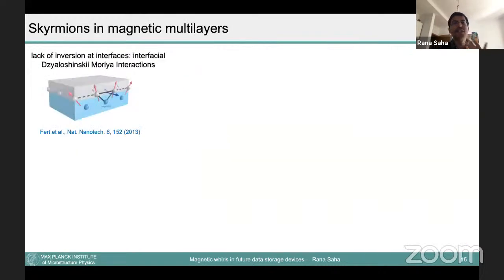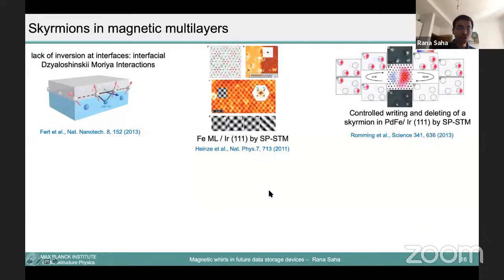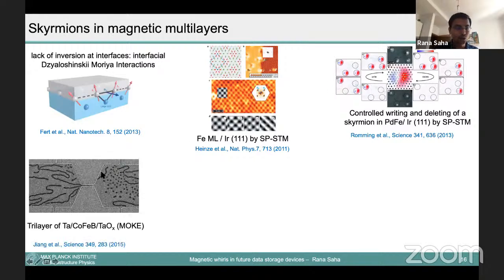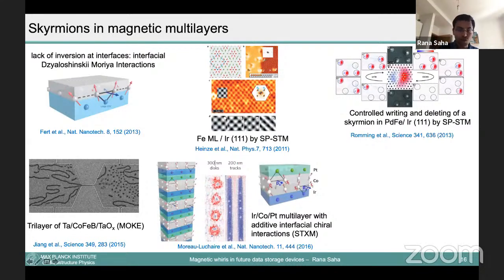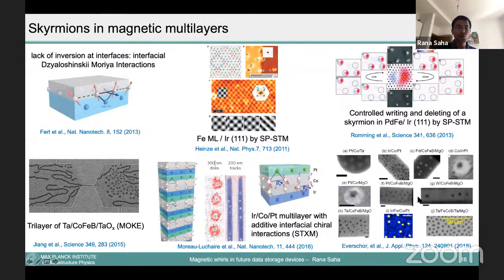You can also stabilize them in a thin film, because for real applications you actually need a thin film in your device. In thin films, people have stabilized them using a scanning tunneling microscope. You can see they can create it and delete it. People have also shown, see, this is some domain wall which bursts into a magnetic bubble skyrmion here. You can also have a multilayer structure, like a multilayer consisting of, say, iridium, cobalt, platinum. You can create some kind of magnetic interaction at the interface of the heavy metal and the magnetic metal. There are many ways you can create skyrmions. So the idea is how you can use this skyrmion for storing data.